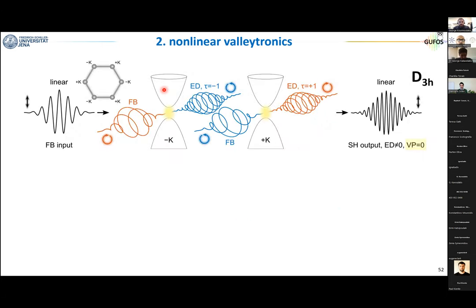But what happens if we shine circularly polarized light? And I want to explain the case with this sketch. Let's say that we start from a material that is at equilibrium, so no valley imbalance. We arrive with linear polarization. Linear polarization is a perfect superposition between left and right circular polarization. Each of them will excite one of the two valleys in a perfectly balanced way. Time reversal symmetry is preserved. The output will be linear. In this case, the electric dipole, that is a broken space inversion symmetry, gives the second harmonic. The valley polarization, that is time reversal symmetry, is preserved. The system belongs to this D3h point group.